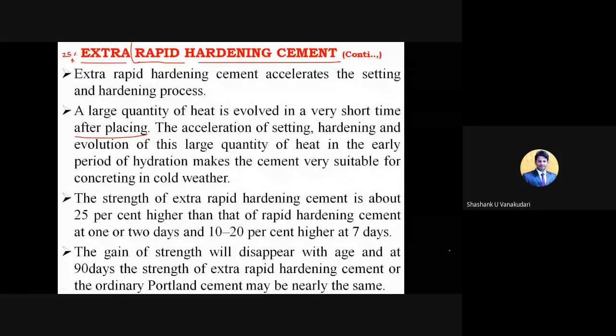After 1 or 2 days, it is going to give around 25% additional strength, but similarly, 10 to 20% after 7 days. Means only in the initial period of time it is going to give higher strength. I mean, in the first 2 days it gives 25% extra, and after 7 to 10 days it gives 10 to 20% extra. And once it reaches 90 days, here they have given that the strength of ordinary Portland cement as well as this extra rapid hardening cement will be similar. Okay.